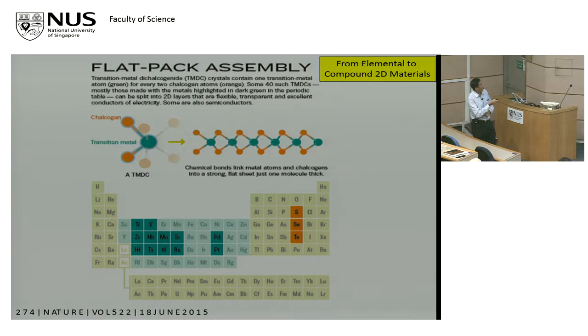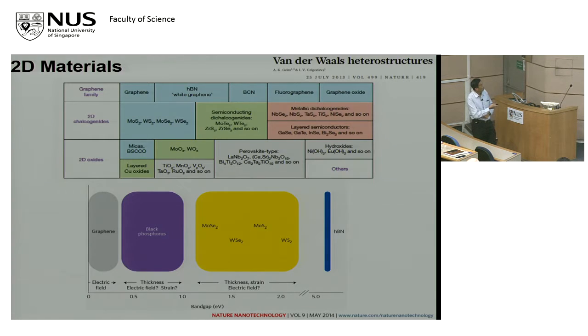So, for example, these transition metal dichalcogenides are now very popular materials. The reason being, well, there are lots of transition metals and chalcogens to choose from and combine. And if you look at the properties, say you look at the band gap, these molybdenum disulfide, tungsten diselenide, they have a band gap that's in a useful range, an optical range, near infrared, and they could be used for devices that could compete with silicon. Okay, black phosphorus is over there. And there are many families of oxides, even 2D oxides people are working on.